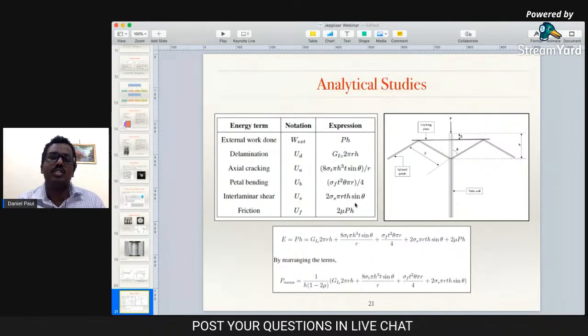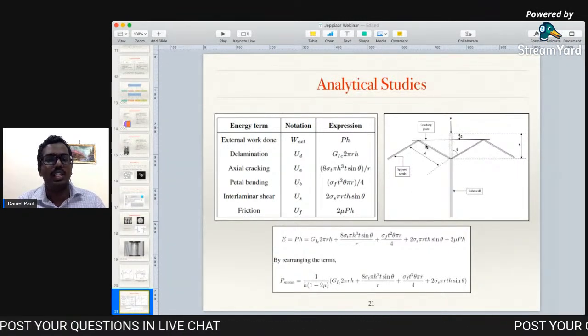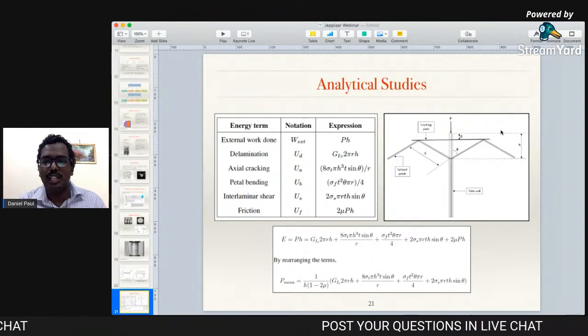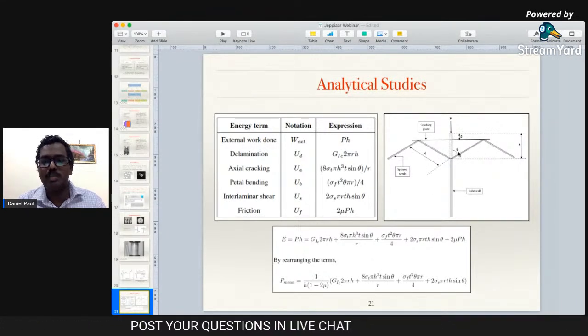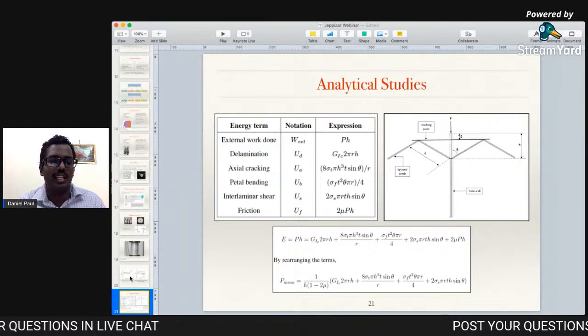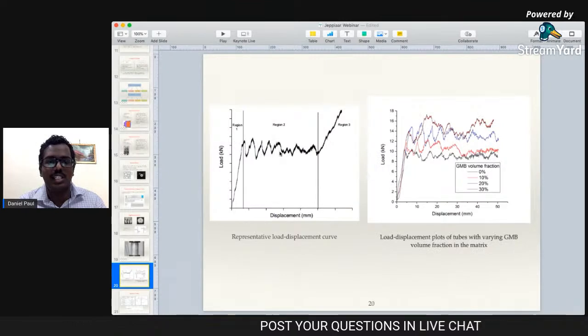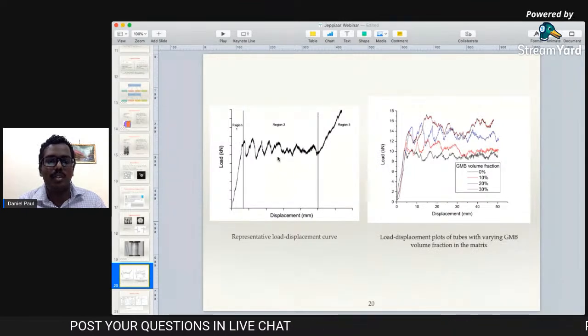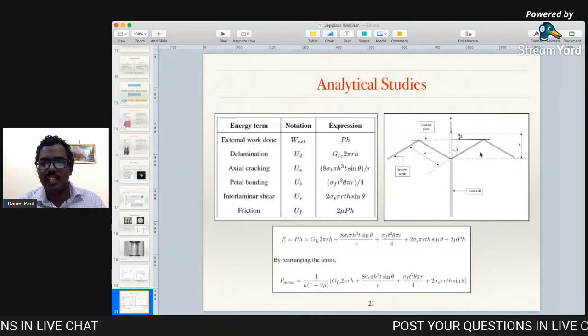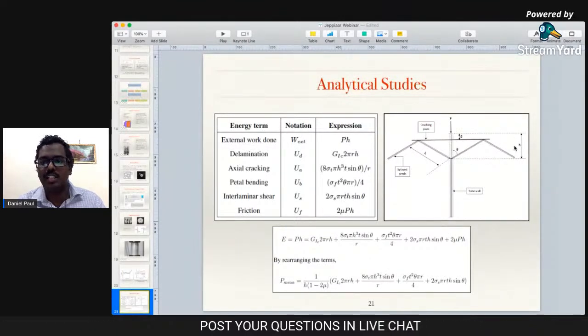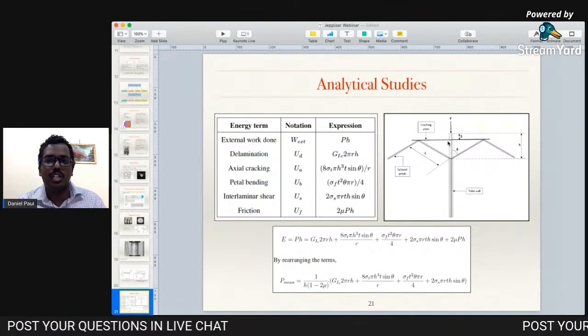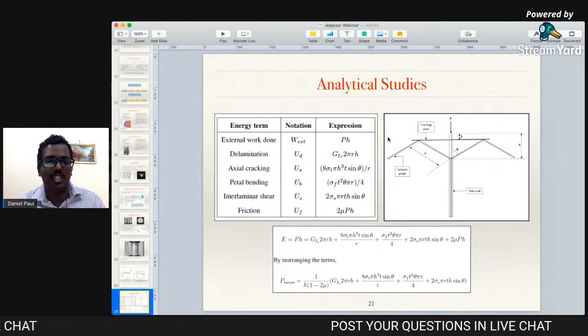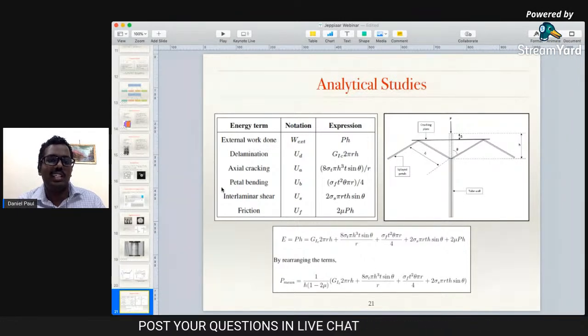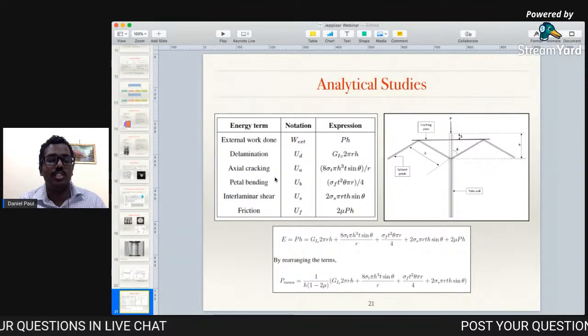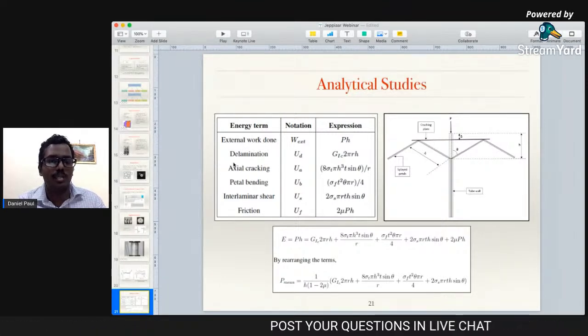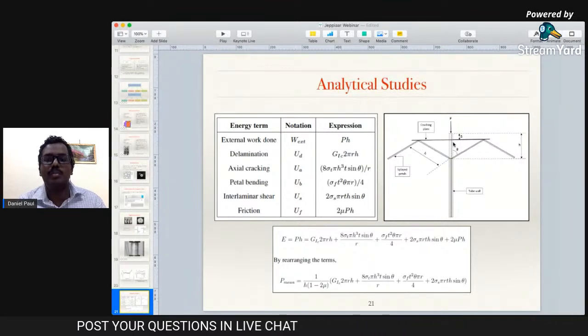and at one point or the other these petals are going to just break off or get damaged beyond any load carrying capacity. So there's going to be a compression, bending, and then the petals break off, and then this cycle will repeat again and again. This is what causes the undulations like this. The undulations are almost of the same displacement. Each cycle length is denoted as h here. It is called a single crush length. At each crush length, we can calculate the external work done, and also we can calculate the different modes of energy absorption or energy dissipation. Because of delamination, there may be some energy which is absorbed.